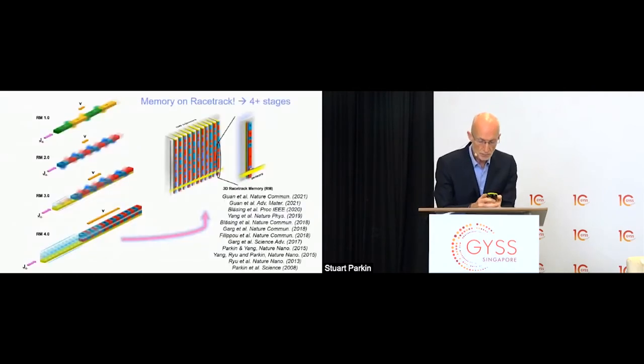I don't really have time to discuss the evolution, but over the last 10 years, we've evolved this racetrack memory, if you like, through four editions, four stages. And these are some of our own work, and of course, there's many papers from other groups around the world. But we moved from racetrack 1.0, in which the racetrack was formed from a very soft magnetic material, just as I've discussed, because in those soft magnetic materials, the current is strongly spin polarized.